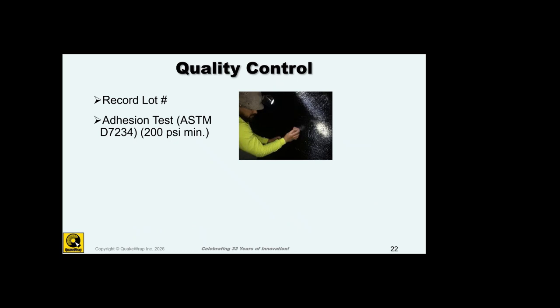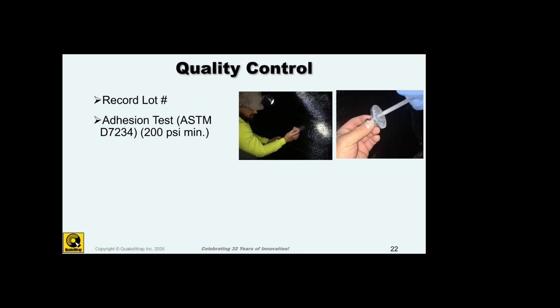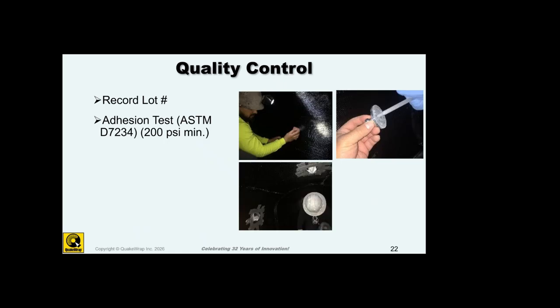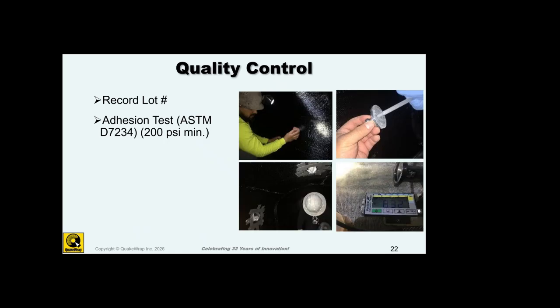Basically, you take these pucks that are 2 inch in diameter, you glue them to the surface of the concrete or the FRP, and then core around it, and with a device you pull on it to see at what load it breaks. And they say 200 psi is the minimum acceptable value. In many jobs, we get 700-800 psi, as you see on the dial here.